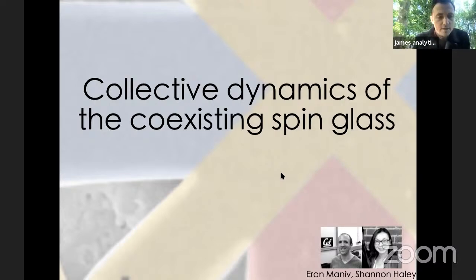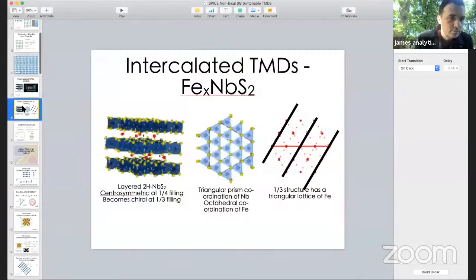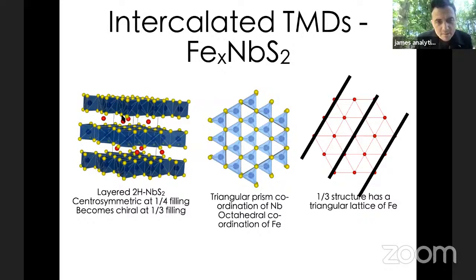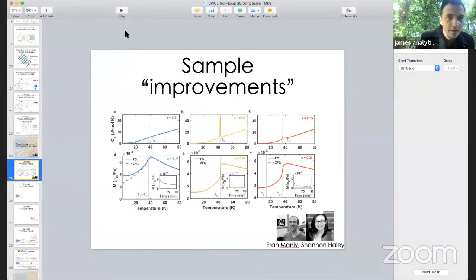So what we're playing with there is, let me just go back to the slide here. What we're playing with here is how many iron atoms are in between the layers. And at 1/3, that's where you have the stoichiometric structure. That's where you have the perfect triangular lattice of the magnetic ion, the iron atoms, and everything else just has defects. You go under, you have more vacancies. You go over 1/3, you have more interstitials, presumably. So we thought what we would see is just more disorder in the systems by just changing this intercalation. But you actually see something a lot more interesting.